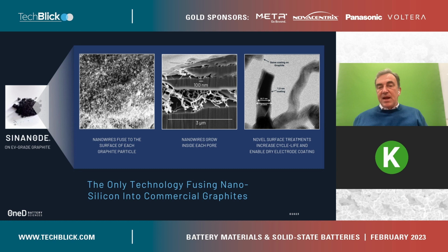We actually developed a way to apply a surface treatment on both the graphite and the silicon that is extremely thin, doesn't add mass. And that surface treatment increases the cycle life. Why? Because it actually stabilizes the SEI that forms during the formation of the cells at the end of the manufacturing line. It also has an ability to stick better with the binders, which allows EV cell makers to use much lower binder content. And everybody in the industry is trying to reduce the amount of inactive material.